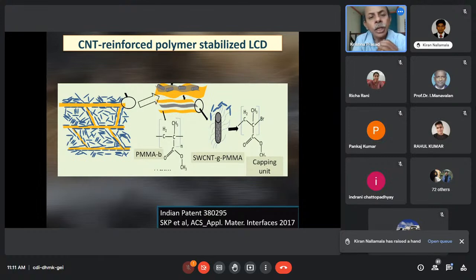The first candidate for that purpose, we thought, is the carbon nanotubes. Carbon nanotubes, of course, as you know, Young's modulus of carbon nanotubes is extremely large. And they also have a shape anisotropy. So therefore, they appeal to the shape anisotropy of the liquid crystal on one hand, but at the same time, rigidity-wise, an extremely rigid system. Can we somehow get these CNTs into the polymer fibers? A lot of liquid crystal groups have been working on putting CNTs into liquid crystals, and then looking at the structure property kind of systems.